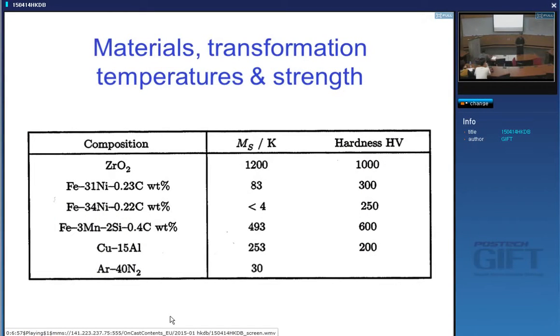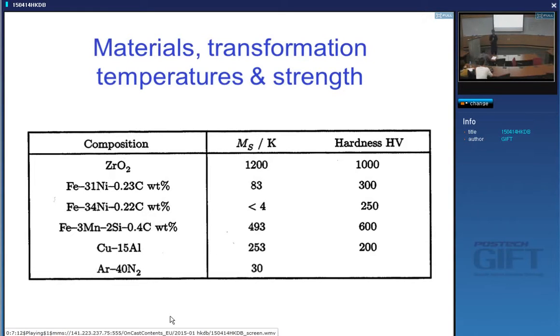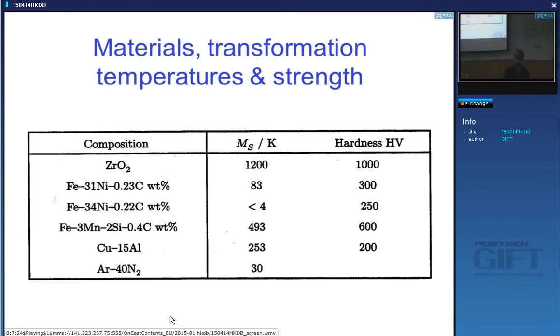You can easily have austenite with one weight percent carbon, like in TWIP steel, but it's not hard. The yield strength of TWIP steel is about 400 megapascals. But if I put the same amount of carbon in martensite, it will be incredibly hard. Why is that? Solubility. How is solubility related to hardness? We are putting exactly the same amount in martensite and in austenite, comparing hardness at the same concentration. So why doesn't carbon harden austenite as much as it hardens ferrite?